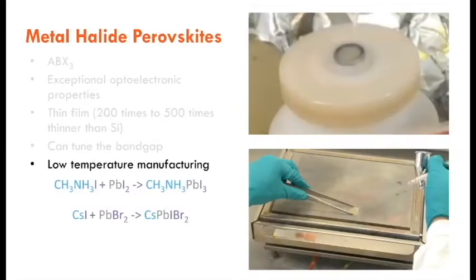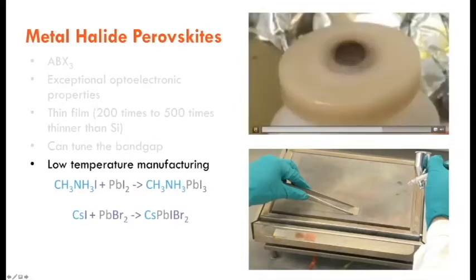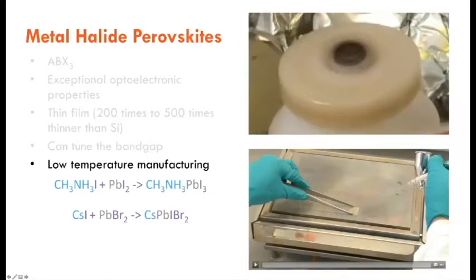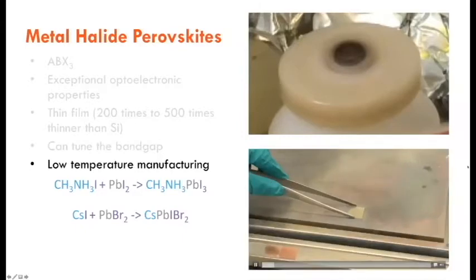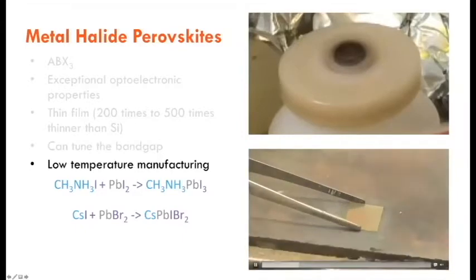What also makes this material so interesting and exciting is that it's very easy to make. Here you can see one of my students making the material. You mix the organic precursor with the inorganic precursor, in the form of salts. You dissolve them, mix them together, and deposit it onto a substrate. You can see the film turns from clear to almost black. It means it has turned into a photo-absorbing, photoactive material. This one is a black film, and here the student is spraying instead of dropping it onto the substrate and spin coating it. You can see it turns orange.